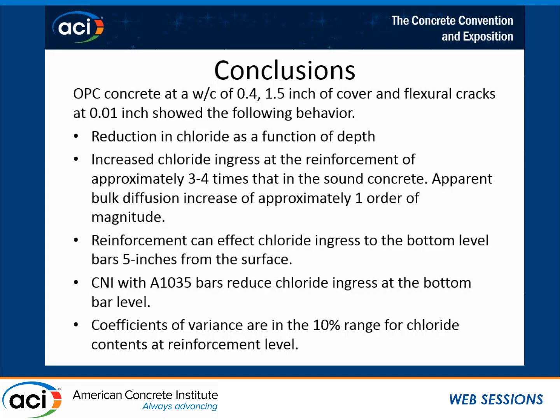Calcium nitrite with A1035 bars reduced chloride at the bottom bar level. Makes sense. These high strength bars, better bond. They can keep chloride from getting down. And the coefficients of variance were surprising to me when I looked at it. When I was putting this study together, I didn't look at it closely, but they're low. I mean, this is pretty reproducible, at least on the same day. I won't say it's going to be close for one set made today and one set made a year from now, but within their set, they're extremely good.